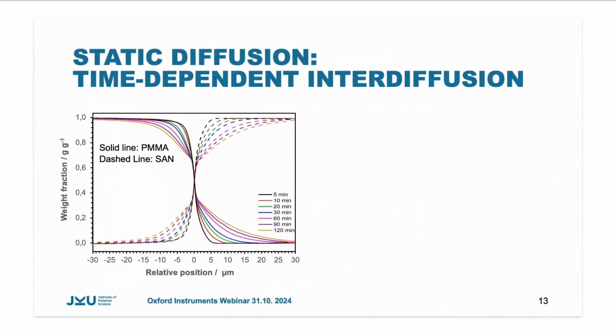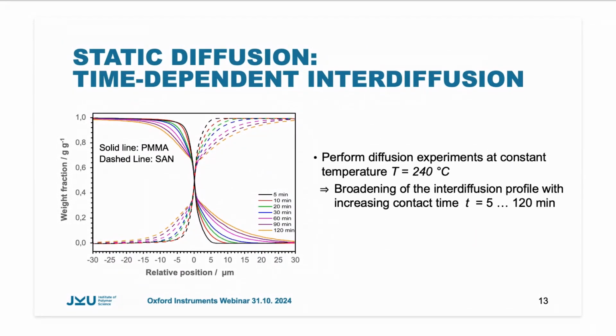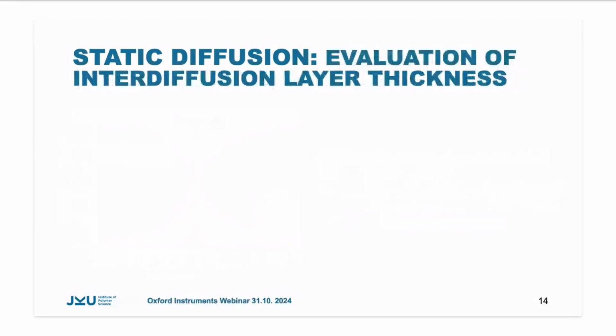So this means we have to do a lot of steps for the data analysis, but this helps us to perform time-dependent interdiffusion studies as shown here, where we have a set of diffusion experiments which are performed at a constant temperature of 240 degrees. What we see for both the lines we plotted for the PMMA and for the SAN is a broadening of the interdiffusion profile with increasing contact time, indicating an increase in the interdiffusion layer thickness, which is quite okay, but it's even here not a value we can correlate with physical quantities.